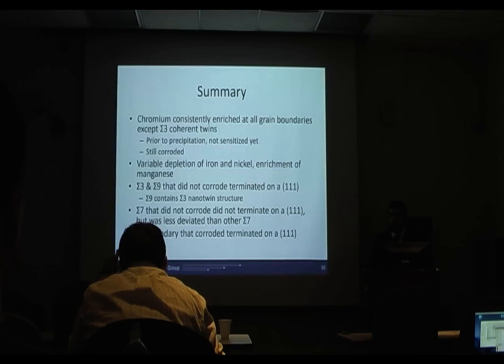Can you remind me what the heat treatment was? For this, it was a one hour sensitization at 675 Celsius. And how was it treated? Did you quench it? It was after the grain boundary engineering, it was quenched, and then we heated it back up to 675 for an hour. So some of these samples, despite being quenched, show segregation. Yes.